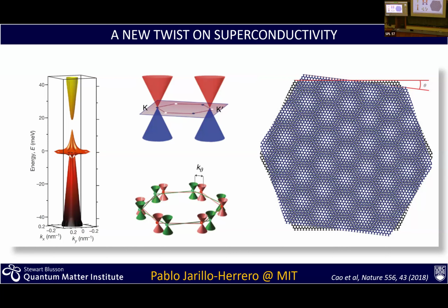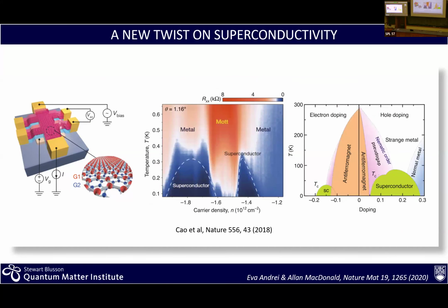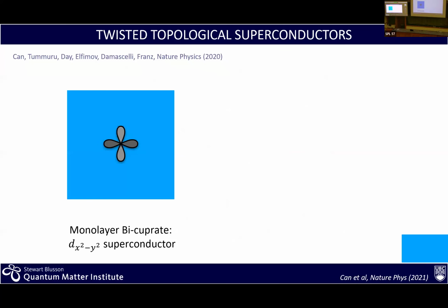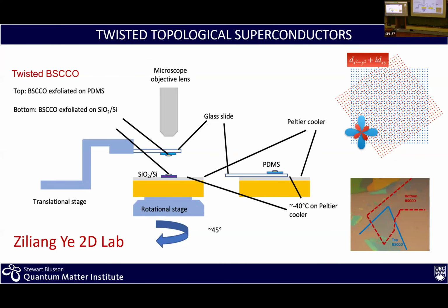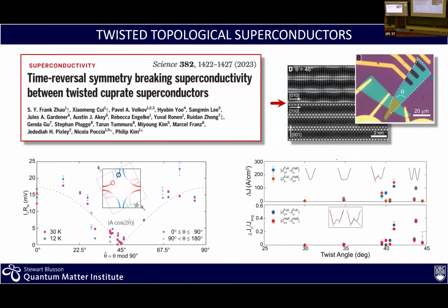And maybe related to this, when we go to the cuprates, I'd like to highlight one aspect of the experiment done by Philip Kim, which is that each data point here is a different device. Each data point is a different device like this one, where you exfoliate at -40 centigrade in some inert atmosphere. You bring the samples together with a controlled angle, and you go from 0, so on top of each other, all the way to 45 degrees and past that.